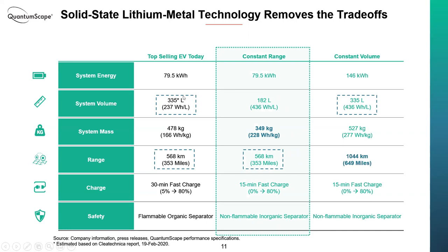So we can cut down from 335 liters to 182, have less weight, and at least the same range. I think it's probably worth highlighting that with less mass, you tend to have better efficiency. So maybe you get a few more miles range, and then half the charge time. So 15-minute charge from 0 to 80% with better overall safety.